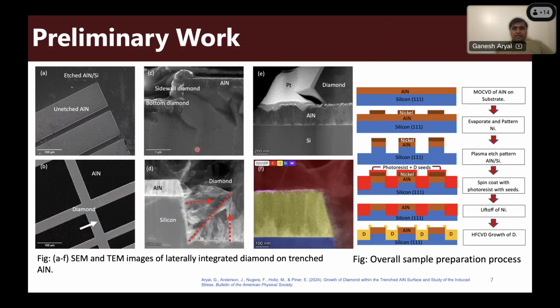We have already experimented on the feasibility of integrating ultra wide bandgap materials. In my master's work, we did the lateral integration of aluminum nitride and diamond, and that work suggested that it is feasible to make a lateral device based on aluminum nitride and diamond. These are the SEM and TEM images of the fabricated device, and this schematic diagram shows the overall process flow. We deposited aluminum nitride on the silicon, then we did some photolithography, and then our dry etching process. Then we did the seeding process of diamond. Then we grew the diamond on the trench part of the aluminum nitride.